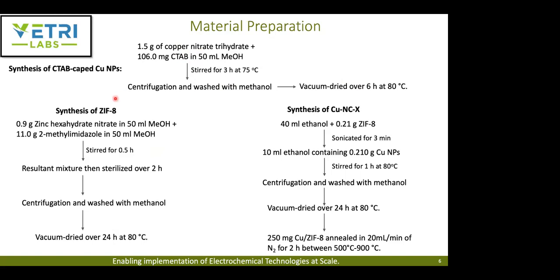Then the ZIF-8 synthesis uses 0.9 gram of zinc nitrate hexahydrate and 11 grams of 2-methyl imidazole, which is MIM in short form, both dissolved in 50 ml of methanol and stirred for about 30 minutes. Then the resultant mixture was stirred over 2 hours, centrifuged, and the precipitate was washed with methanol and vacuum dried for about 24 hours at 80 degrees Celsius.